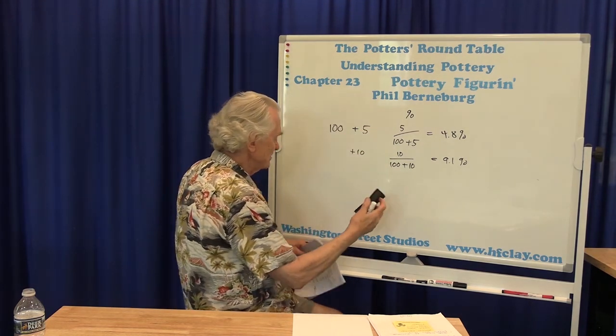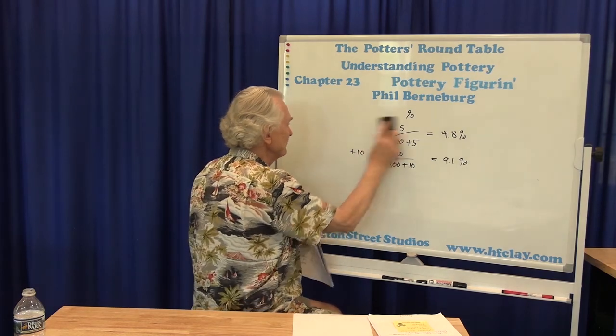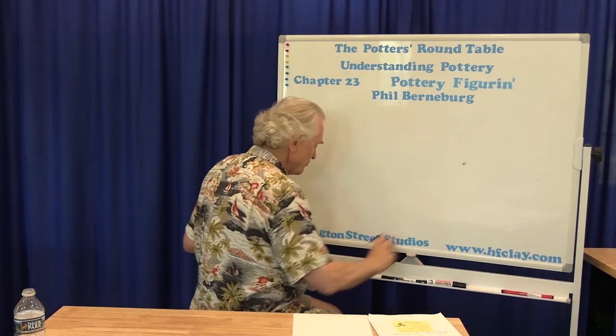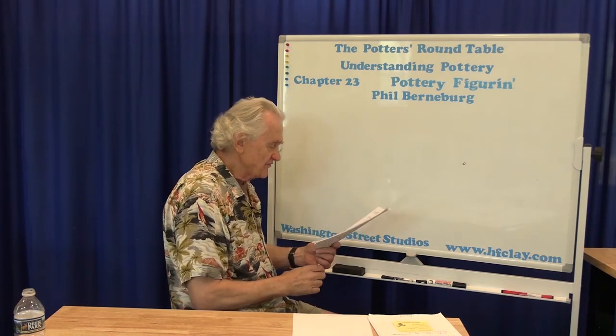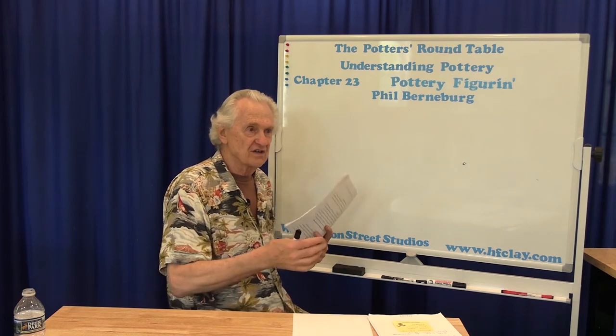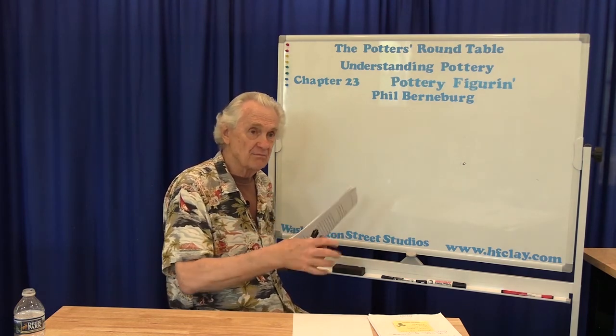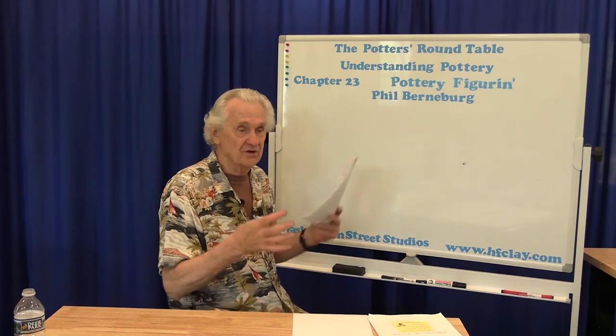But there's another procedure, kind of a shorthand way of doing it, which is even simpler. I only make up one batch, and it's only approximate, but it's a great screening technique. Some people call this the blender method, because basically I'll make an addition, mix it up, take a sample, make another addition to the same batch, mix it up, and take a sample. And typically you could do this in a blender, so you get really good mixing.